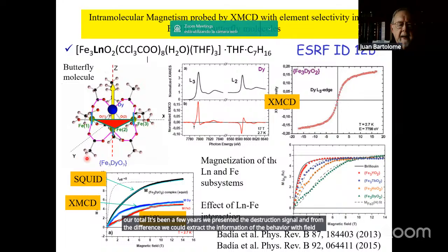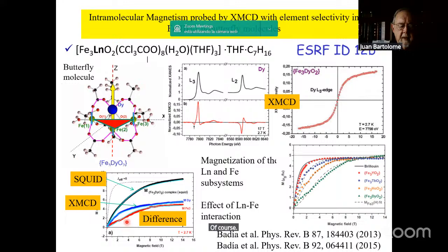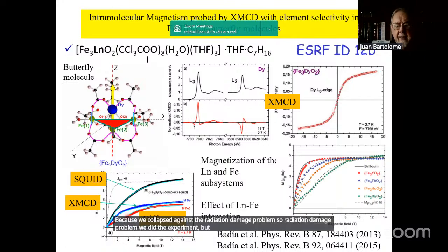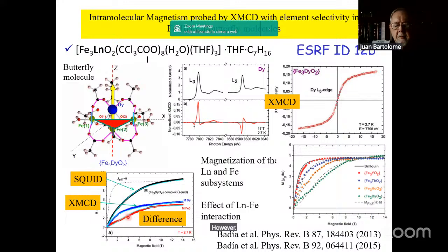of the iron-3 sublattice. Of course, one can think, why not measure directly at the iron L2,3 edges, for example? Because we collided against the radiation damage problem. So we did the experiment, but it was not successful. However, from this difference, we could obtain the iron sublattice behavior. Here I show you a comparison where these results are collected.